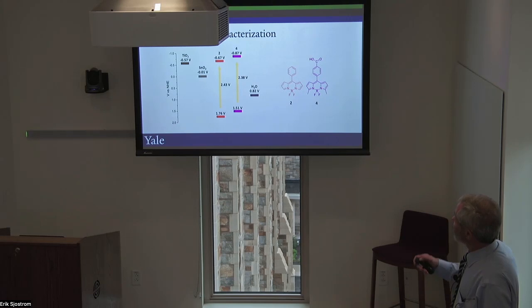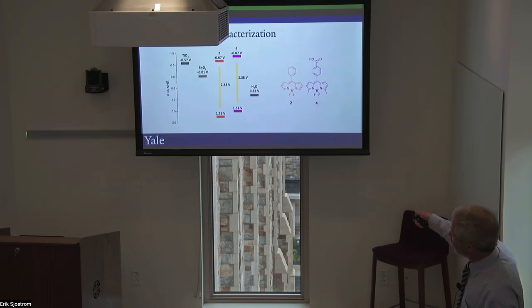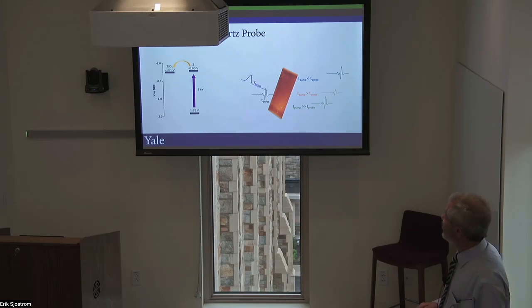Does it work for water oxidation? So these are some comparison of voltages for electron band edge for TiO2 and tin oxide at neutral pH. And we measured the ground state potential electrochemically for BODIPY and also the carboxylic acid version, and the excited state potential, which is done by using the absorption energy. And what we see is that the predicted potentials of the excited state are more negative than the band edge of either TiO2 or tin oxide. So it would predict that there would be an injection reaction, an electron transfer reaction. And indeed, that's what we observe by using terahertz spectroscopy.